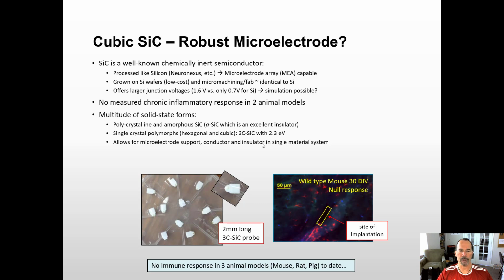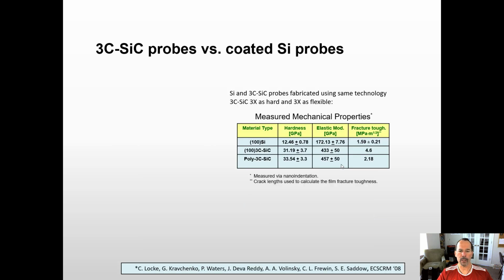So that's our goal. One last thing about mechanical properties. Here we see some nano indentation data from the past, where we have basically compared the hardness, the elastic modulus, and the fracture toughness. So we see in all cases that cubic silicon carbide, and these are thin films, compared to bulk material. So it's even more skewed in the advantageous side for silicon carbide. We have about 3 times the hardness, 3 times the elastic modulus, and quite a large factor of improvement over fracture toughness. The material just doesn't like to fracture. And just as a comment, diamond has this problem.